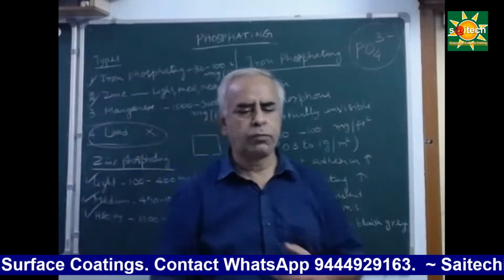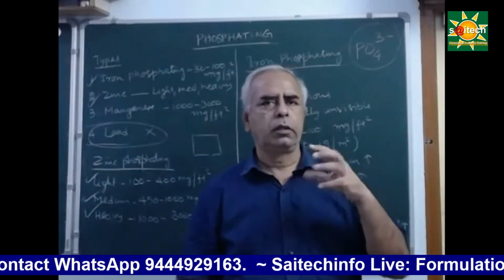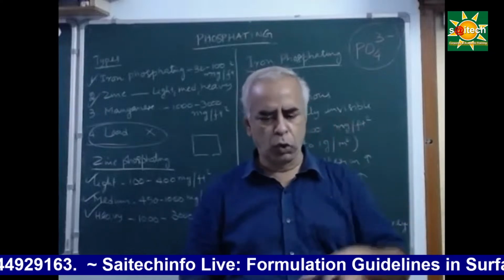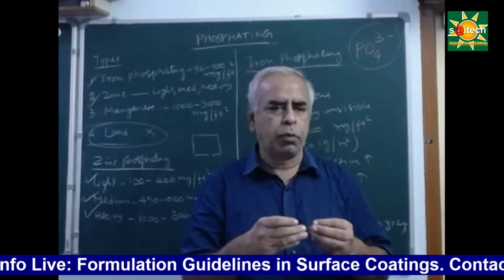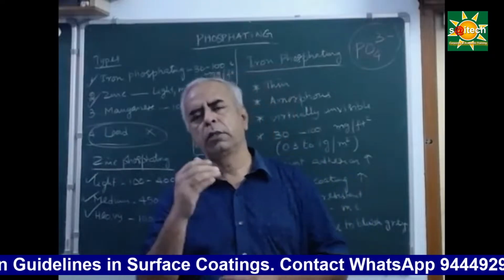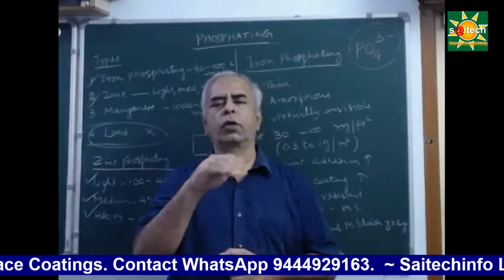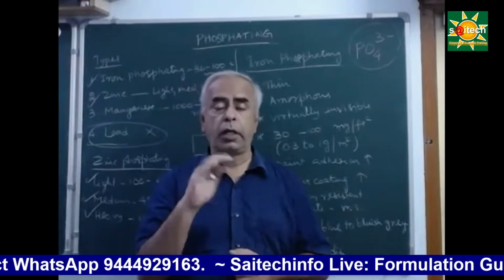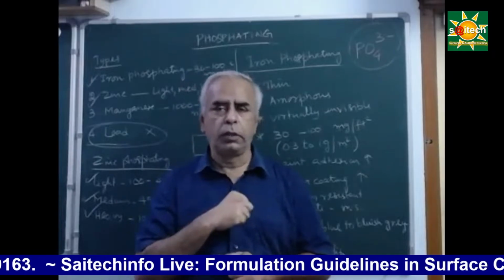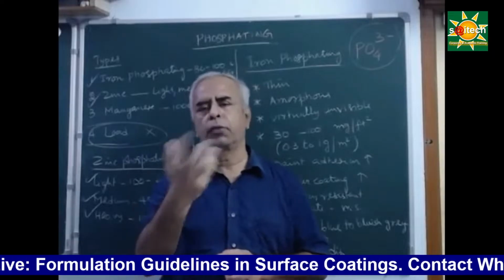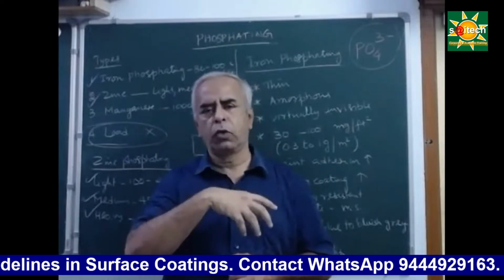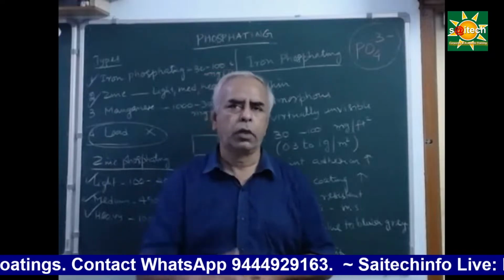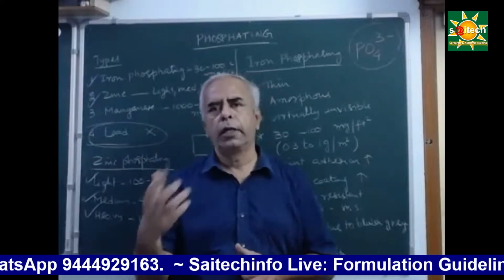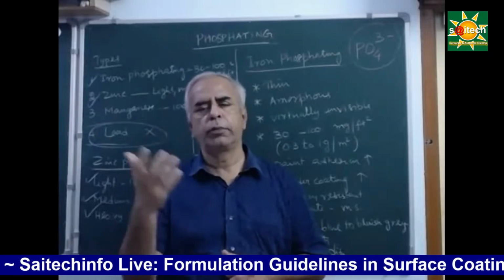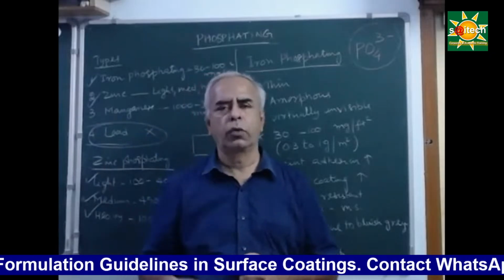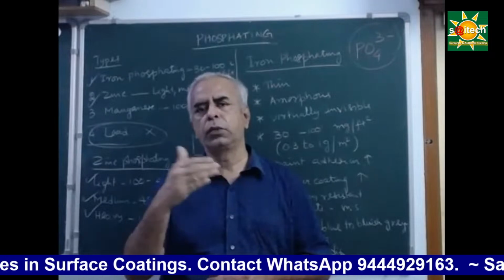With the increase of coating weight, the coating roughness will be more, and there will be a lot of porosity also. If there is more porosity, that is not good for corrosion resistance. But at the same time, it can absorb oil and waxes, and for that purpose a heavy coating is recommended. For corrosion resistance, by painting, either liquid paint or powder painting, you can go for light to medium.